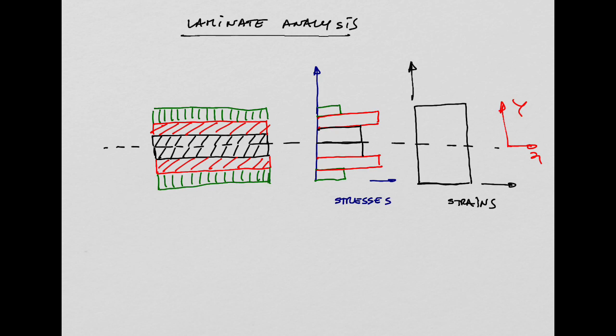So this is quite important. For example, if you think of a pressure vessel, again, you might have several plies, not only one. When you apply pressure inside of the vessel, you are going to impose a deformation, and the walls of the pressure vessel will deform as a whole, a uniform deformation for all the plies of the laminate. But when we apply the stiffness to obtain the stresses, because the plies have different orientations, they will have different levels of stress.